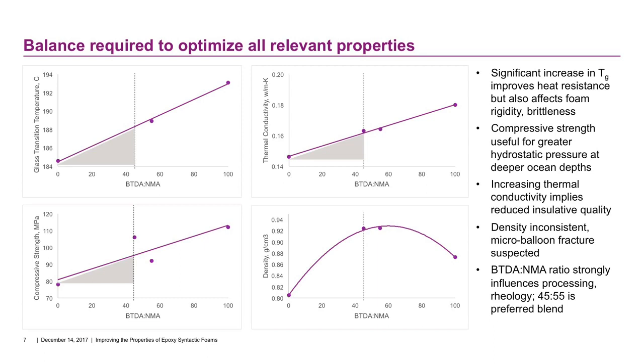In order to get that, we've come up with a recommended blend of 45 to 55, and as you see on the various graphs, that amount affords you a nice kind of a compromise figure in each sense, where you gain an improvement in properties, and so you can address in-service performance as well as processing performance, in the plant environment.